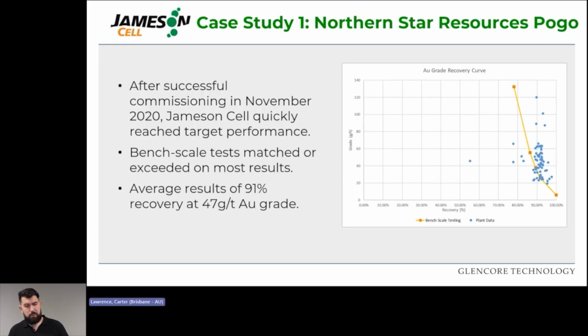So the cell was commissioned in November of 2020, and very quickly the Jameson Cell hit target performance. You can see on the graph on the right, the orange bar there is the bench scale testing, and the blue dots are plant data. Very quickly, the bench scale tests were matched or exceeded on most results, with an average result of 91% gold recovery at 47 grams per ton of gold, and that's from the flotation feed in the rougher circuit.